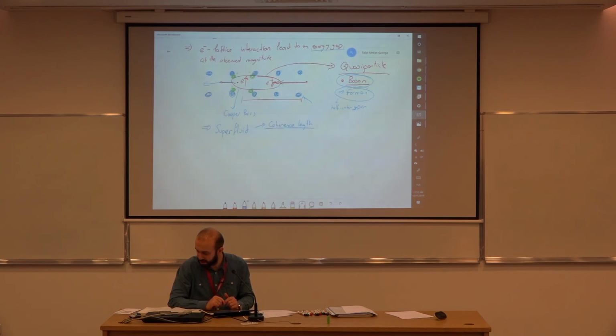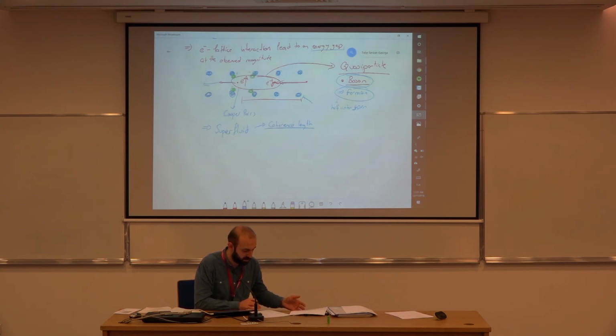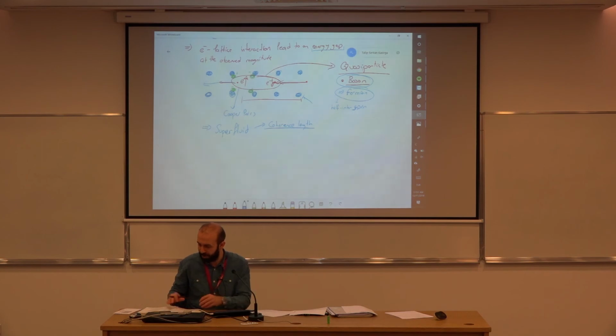And the ratios that we are talking about, I've noted it down, are not too high. Even 1 in 1 million or 1 billion is enough to destroy the superconducting order. So if you have a few iron atoms in a niobium crystal, that's enough to change the transition temperature. And as you increase the number of impurities, the transition temperature decreases gradually, and at some point it reaches 0.